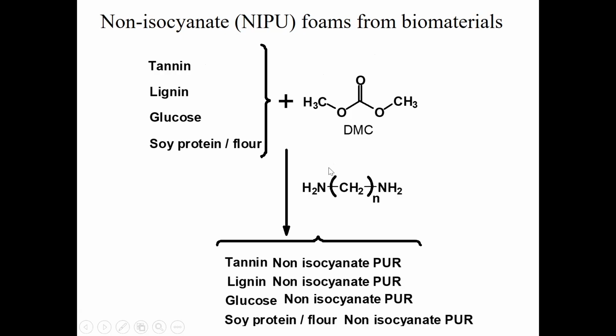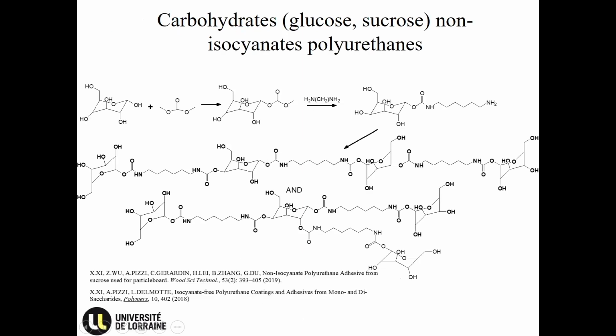And then with a diamine or a polyamine. Here, the diamine was the original one that we used, but also with polyamine. We even arrived at putting amino groups on a tannin, and having tannin, dimethyl carbonate, and aminated tannin. And you form tannin non-isocyanate polyurethane, lignin non-isocyanate polyurethane, glucose non-isocyanate polyurethane, and soy protein, the same. And the results for particleboard are very good.